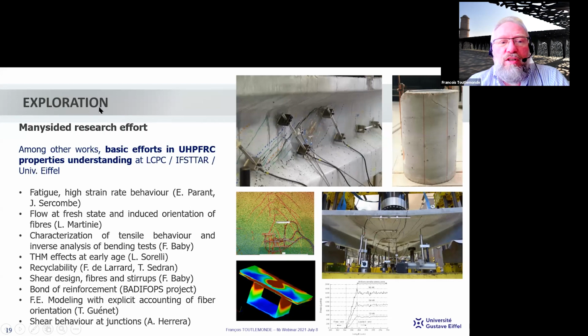This phase of exploration was accompanied by a many-sided research effort. In my institution we had many PhD theses on structural behavior: fatigue, high strain rate behavior, flow at fresh states, characterization of tensile behavior using bending tests, effects at early age, recyclability, shear design, and bond of reinforcement. We instrumented rebars with fiber optics to demonstrate the very short anchorage lengths of rebars in these materials.